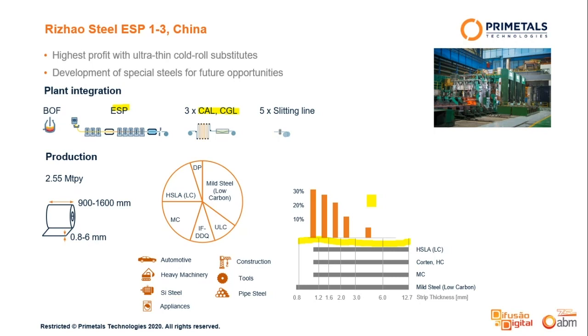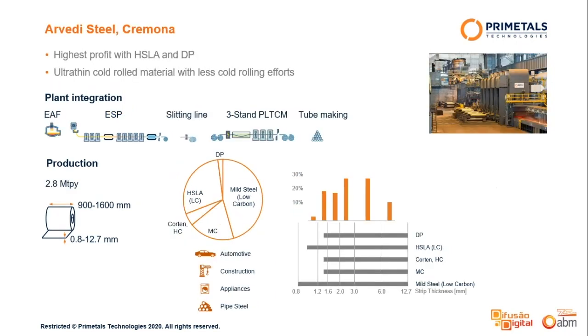Nevertheless, Rizhao starts to develop also advanced grades and silicon steels to be ready for the future when the current business is changing. Also important to say is that the plant is already exceeding the nominal capacity of 2.55 million tons and is running very well. While Rizhao Steel supplied the liquid steel from a BOF route, Arvedi ESP is using an electric arc furnace route.